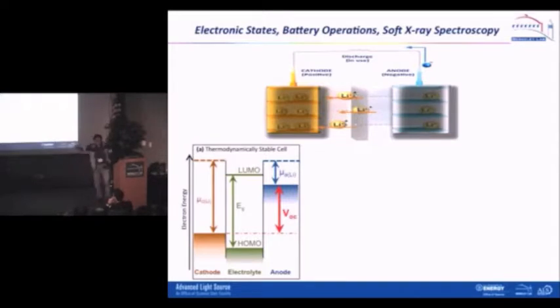And in the meantime, you are limited by the so-called electrolyte window. It's the lowest unoccupied molecular orbital and the highest occupied molecular orbital. So if you have this energy level sitting above that, you will reduce the electrolyte, or if this is lower than that, you will oxidize the electrolyte. So although you want this voltage to be as high as possible, you cannot go above this limit.